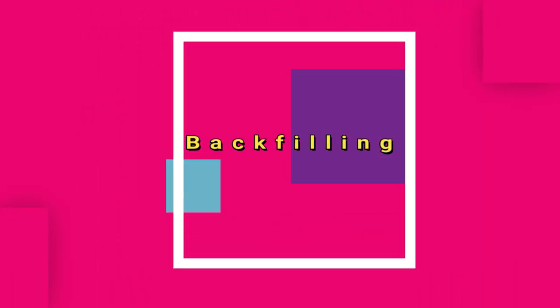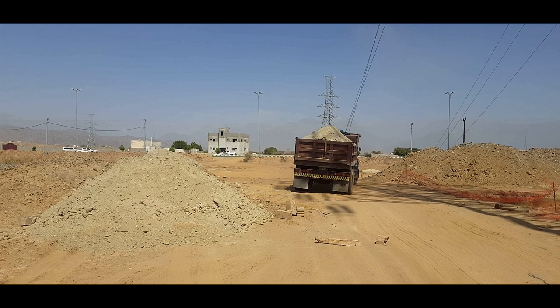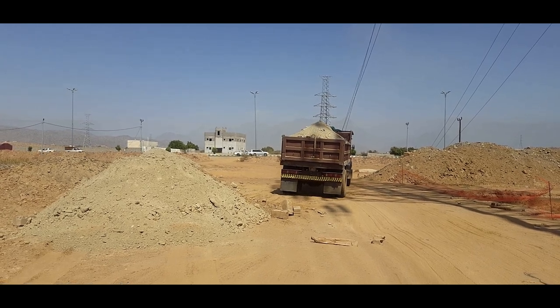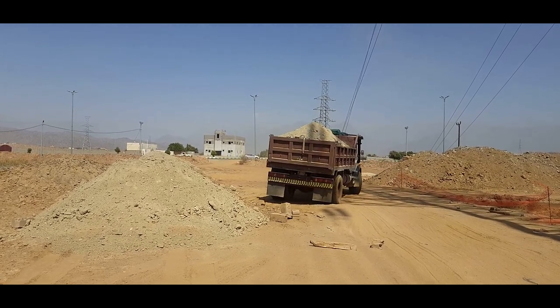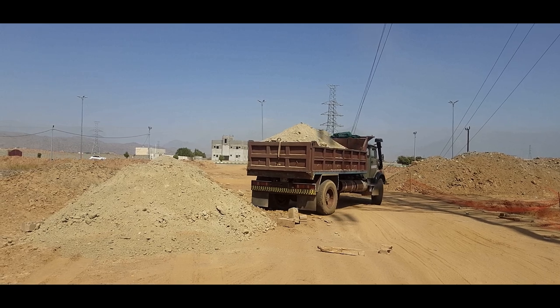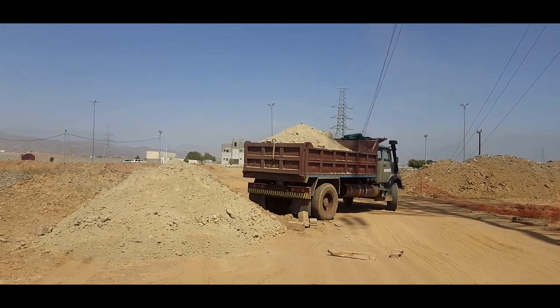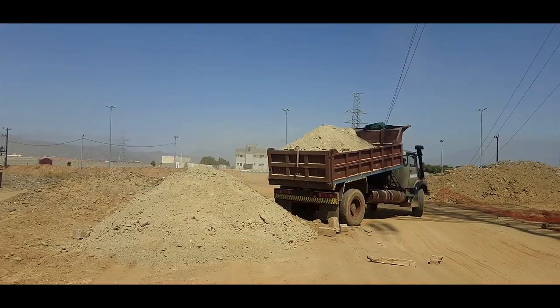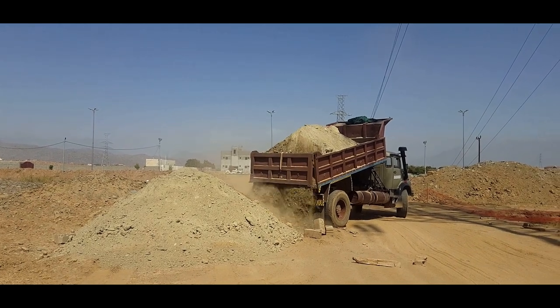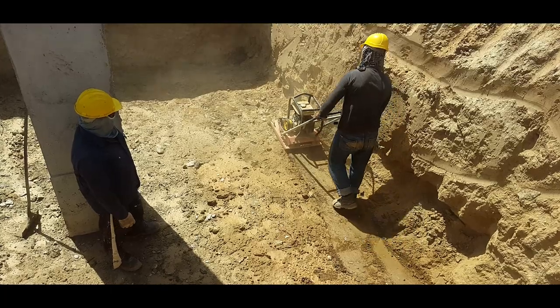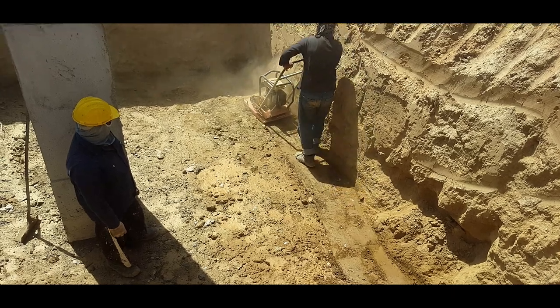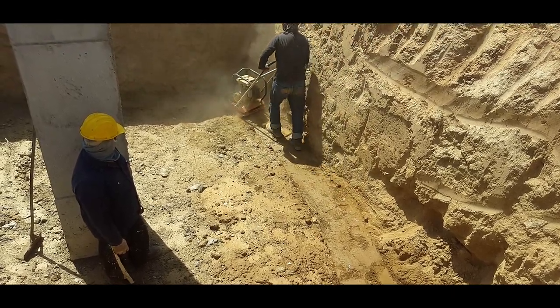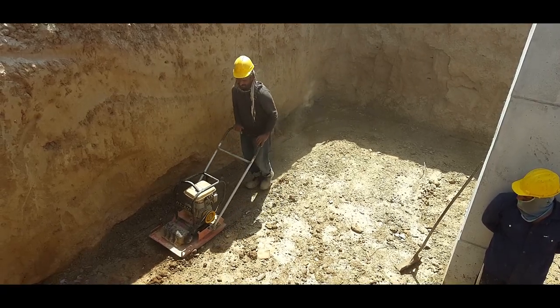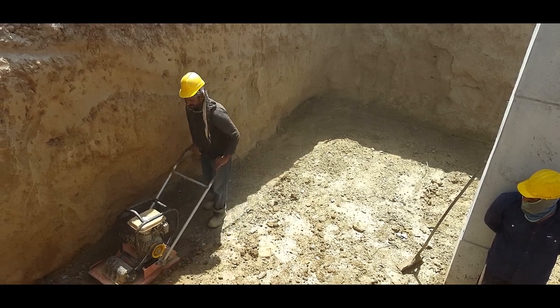Backfilling. The backfill material shall be free of organic matter, rubble, cobbles, boulders and other deleterious substances. Maximum particle size allowed is 100 mm. Backfill material is to be placed in uniform layers not exceeding 200 mm. Each layer needs to be compacted properly. It is advisable to remove the props after the backfilling is over.